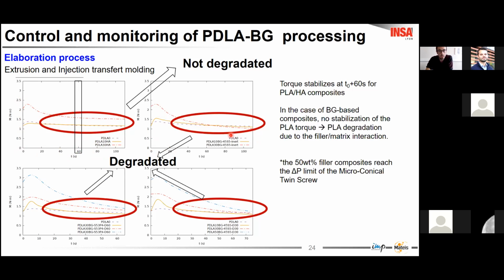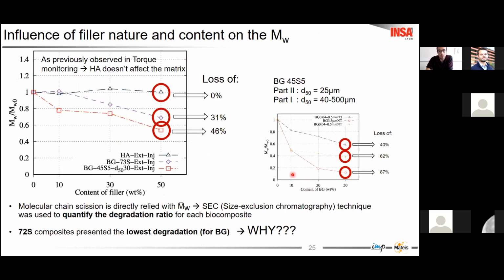The viscosity decreases over time, but not in the case of hydroxyapatite. As previously observed in the torque, here in the size exclusion chromatography, hydroxyapatite doesn't affect the matrix.